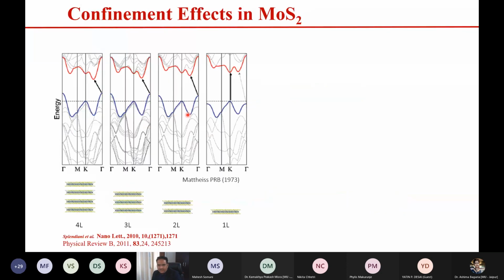which is a very, very exciting material because it has thickness-tunable physical properties. So if you look at the band structure of MoS2, this is the energy versus momentum. If the layers are large, let's say it is the bulk, it is an indirect band gap semiconductor, and the band gap is 1.2 eV, which is close to the visible region. If you remove layers and have 3 layers, the band gap changes. If you have the bilayer, the band gap changes further.